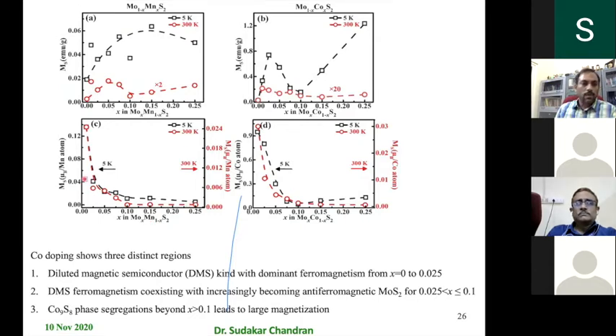You can also measure the Bohr magneton per dopant atom, which shows a gradual decrease. So which means, this is the typical nature you will find in dilute magnetic semiconducting systems. So this particular system behaves just like dilute magnetic semiconductors. So this study showed that cobalt doping seems to be promising. Of course, there is always a question of whether the cobalt segregation is happening, which is contributing to the magnetic signal.